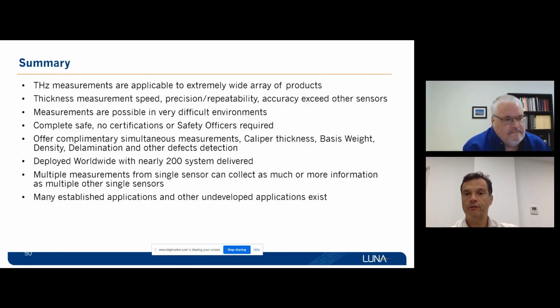A couple here from Christophe Riviere again. He's got some questions. How much time does it take to measure a 1 inch square surface, for example? And what is the terahertz frequency range used in your systems? So the terahertz frequency range, as I said, typically ranges between 50 gigahertz up to 3,000, and in some very rare cases 4,500 gigahertz, or 4.5 terahertz. Although most of the time, a lot of things only transmit well up to about 0.8 to 1 terahertz.